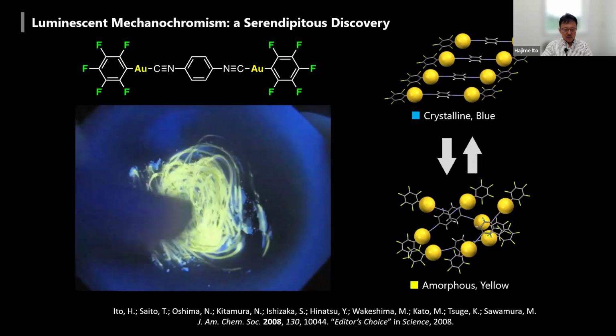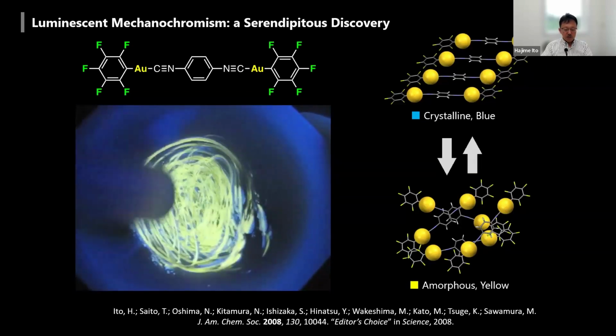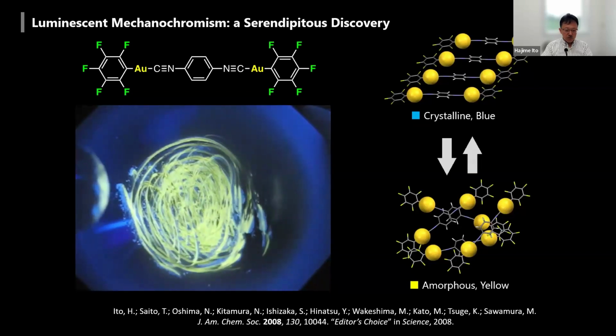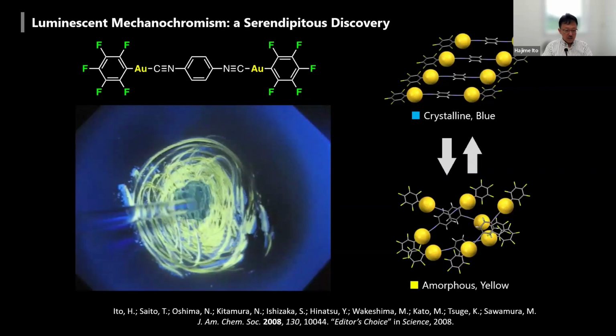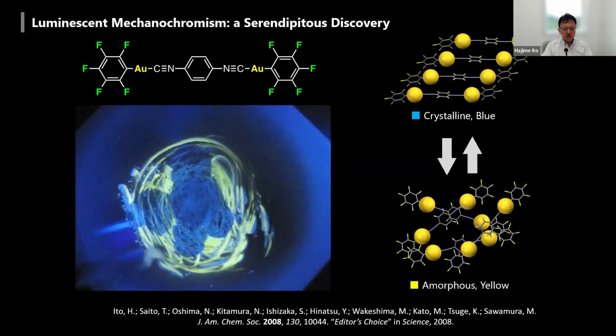More interesting is that this yellow color can be reverted to the original blue color by addition of solvent. In this case, we use dichloromethane. As you can see, this yellow color can be reverted to the original blue color. This is very similar to just a recrystallization from amorphous state to microcrystalline blue luminescent state.